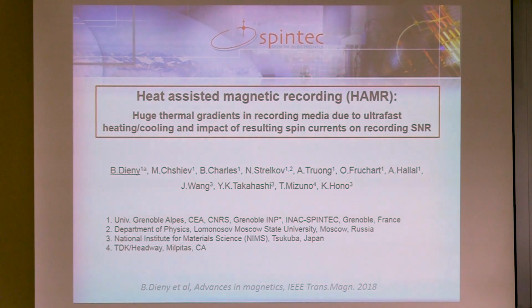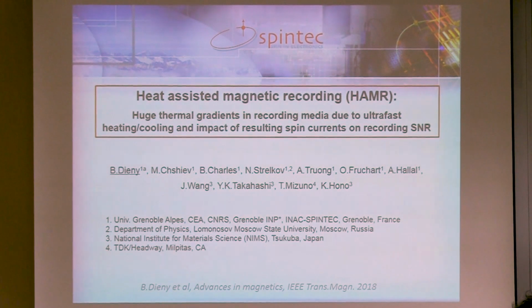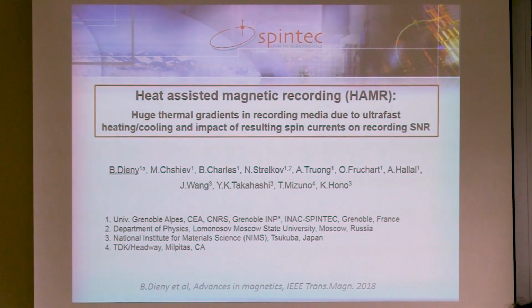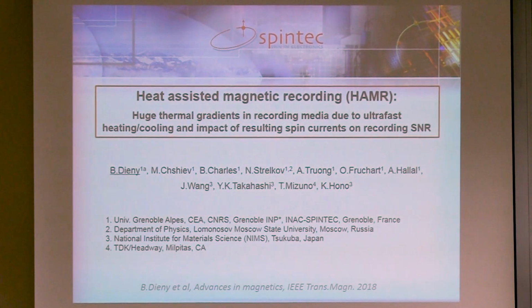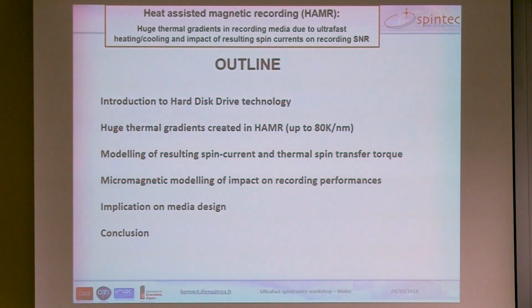And I will show that these thermal gradients can induce spin currents in the media and induce an effective coupling between the grains in the media during the recording. And this coupling has consequences on the recording performance. So somehow, I will discuss ultra-fast phenomena, which take place in a practical technology, which is heat-assisted magnetic recording.